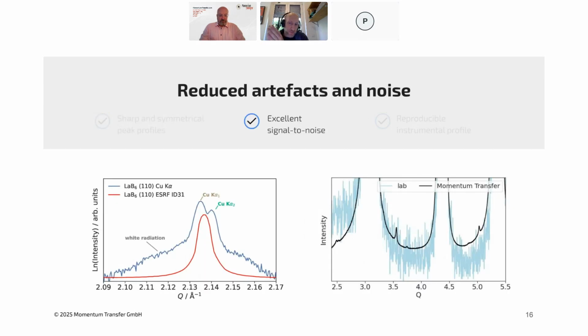Another thing is that because we have very high flux X-rays, we can get a very good signal to noise. And also coupled to that, having a monochromatic wavelength allows us to reduce significant artifacts from other wavelengths in the measurement. So on the left-hand side here, you see a comparison of a copper K-alpha system. It has essentially a nickel K-beta filter, but you still have copper K-alpha 1 and 2 signals, which are the two significant emissions from a copper K-alpha system.